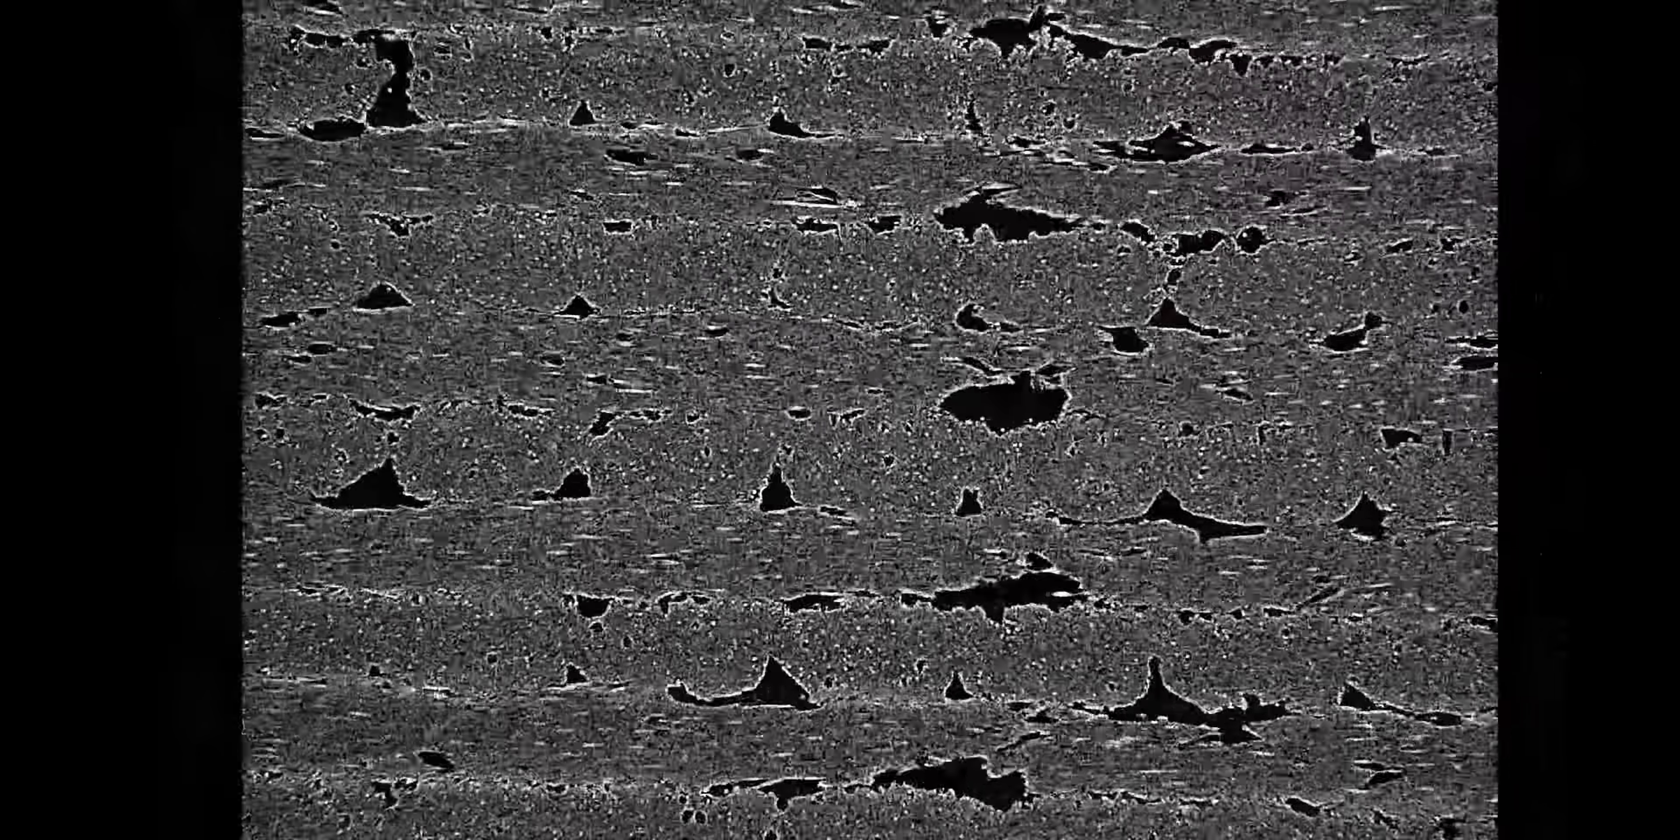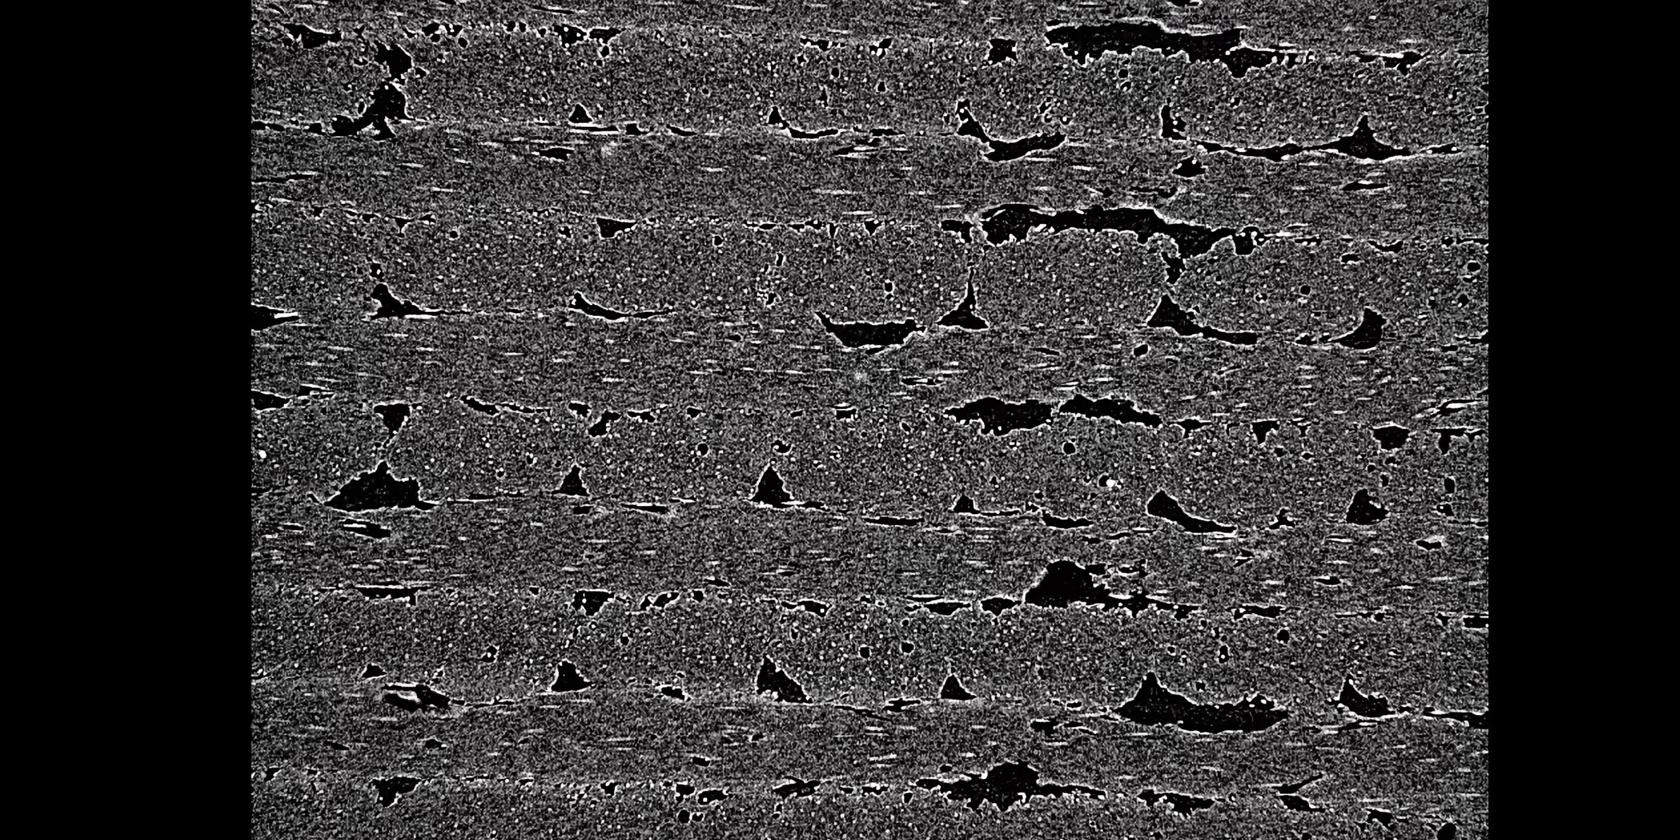So I'm done with reconstructing my CT images, and yeah, as I suspected, the voids are real, first of all. They are actually inside of the filament or of the printed part, not attached to the carbon fiber itself. So I don't exactly know what those voids are and if they even come from carbon fiber reinforcement, or if they're in every extrusion of a polymer. If you want to see a video about that where we compare, for example, carbon fiber and normal ones just in those voids, let me know in the comments below, and we will do a series on micro CT-ing different kinds of 3D prints. But let's get back to topics.